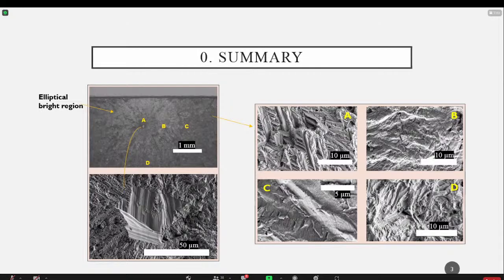The first one is surrounding the very first 300 microns around the defect, and you can see it's labeled A, and it's a very microstructurally textured region. So you can clearly see how the crack evolves following the acicular martensitic structure, which is typical of these titanium alloys. Next, as we go farther from the defect, we observe a very irregular region, which is labeled B,